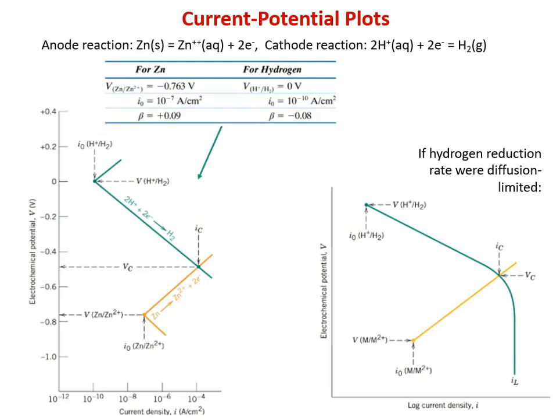Now sooner or later something's going to pile up and we're going to be limited by mass transport. And like I said, cathodic reactions tend to be more kinetically inhibited. In this case, it also takes a while to get rid of the hydrogen gas, so we will actually hit limiting current in terms of having to diffuse things in and away for the cathodic reaction here first.